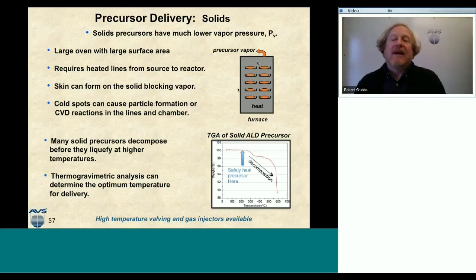But if you're heating this, you have to make sure that all of your lines from your furnace or from your solid precursor are heated to a slightly higher temperature than the furnace itself, because you don't want any of these solids to condense in your lines, because then you'll have particle problems, or you'll cause CVD to happen in your precursor delivery lines. Then you'll have to get one of your grad students or some subordinate to clean it out for you, and you don't want to do that. The other thing that can happen with solids is that you can form a skin on top of the solid.